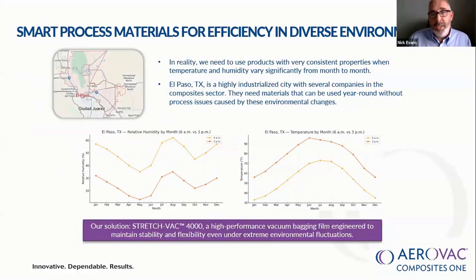One of the issues we've been hearing from our customers is that there's a requirement for a high performance bagging film, especially when we consider Aerovac supplying materials all around the world. When we look at those environmental conditions, for example, here in El Paso, Texas, where we've got really high temperatures and really low humidity, this can have a detrimental effect on some nylon bagging films. The feedback we were getting from customers is that they'd really like to see a tougher film that can cope with these temperatures and humidity levels, and also a film with higher mechanical properties, so a higher tensile strength and a higher elongation.